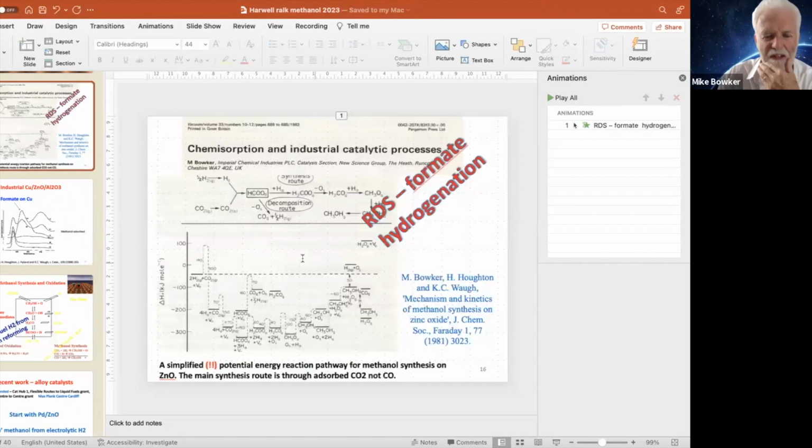So the role of the vacancy is that when we did those very early experiments, we found that it was necessary to treat the zinc oxide surface first at a mildly low temperature in a bit of hydrogen. And the role of that was to make vacancies. We could see those vacancies by detailed XPS measurements. Second thing is, as I said, CO2 calculations for zinc oxide indicate it adsorbs very weakly. When we use the not reduced zinc oxide, we can't get these high temperature states in TPD.